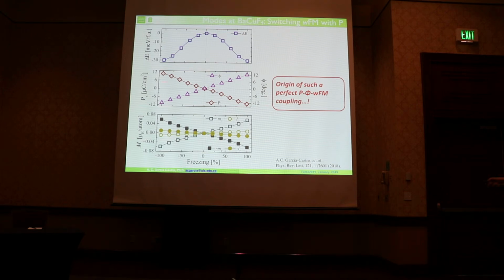Now, when we look at the polarization, we see clearly the switching of the polarization, which is close to 11 microcoulomb per centimeter squared. And when we look at the rotation, we have exactly what we expect, the full change on the rotation. Now, if we look at the magnetism and the weak ferromagnetic component, which is close to 0.0706, we have the full switching of it. In here, we can see that we have the magnetic moment and the orbital moment. We just extracted it to see if there was a strong contribution from it. It's not that strong, but the most important one is M.